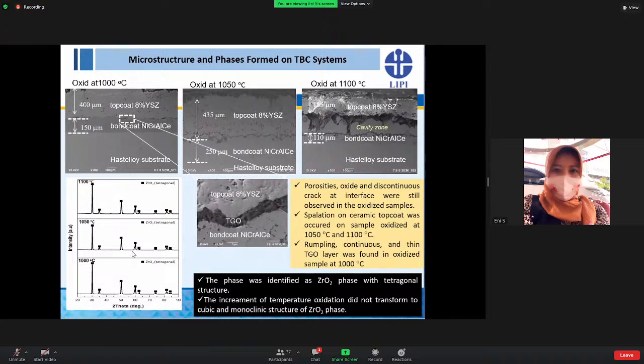Further, we also characterized by XRD, and it shows that all the coating samples, even though the oxidation was carried out at different temperatures, are again majorly composed of the tetragonal zirconium oxide phase.